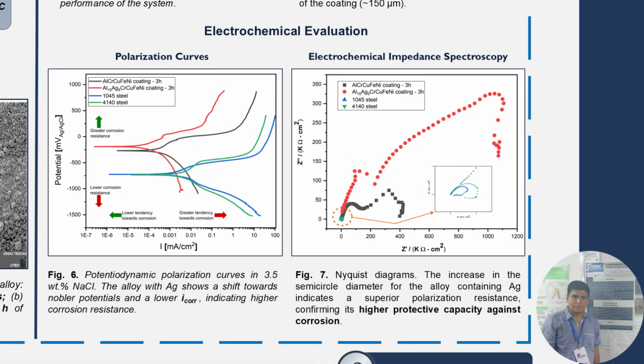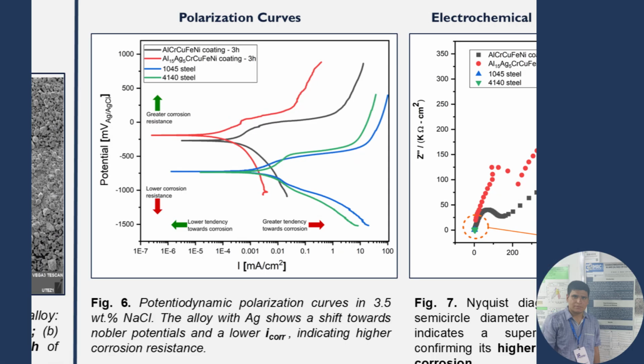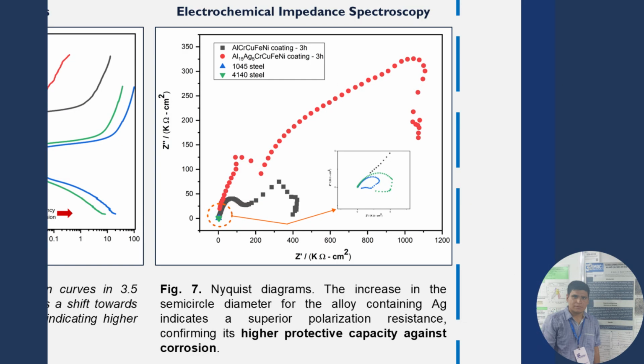Finally, the electrochemical evaluation in a 3.5 weight% sodium chloride solution highlights the benefit of silver modification. The potentiodynamic polarization curves exhibit a distinct shift toward nobler potentials and a significantly lower corrosion current density for the silver-modified coating. This superior protective capability is fully validated by the Nyquist diagrams from electrochemical impedance spectroscopy, where the larger semicircle diameter for the silver alloy confirms a much higher polarization resistance against aggressive saline environments.